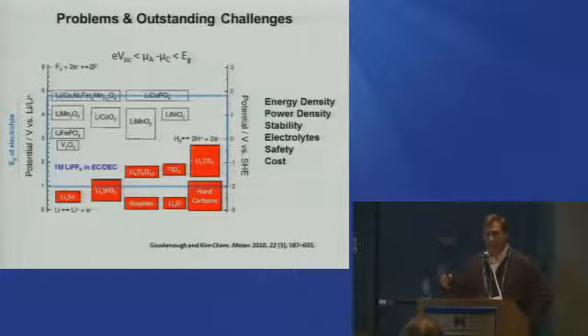He recognized very early on that you could tune the redox potential of a solid by substitutionally adding ligands, in a sense. We can think in the solid state sense, not the molecular sense, where you can actually raise the oxidation potential of the cobalt 3+/4+ by putting in phosphorus rather than oxygen. These potentials get so high that oftentimes they fall outside of the potential window of stability of the solvent that holds the lithium ion salt. In fact, a lot of these materials can be made by high temperature solid state synthesis, but we can't study them because we have huge degradation problems, decomposition layers that form due to these highly oxidizing potentials. The same is true for other anode materials that you might have heard about, the silicon and the tin analogs.